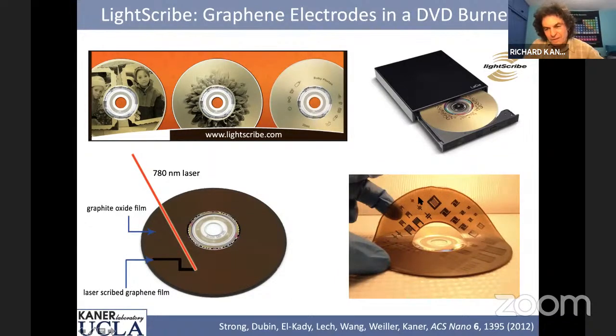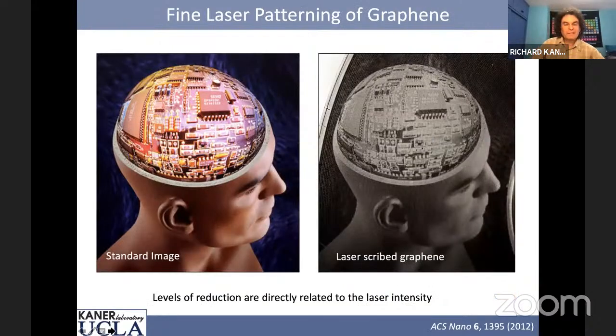So this is graphene oxide on plastic. You can see the golden brown color. You hit it with the laser, and you can draw little circuits. And so basically what we're doing is we're creating graphene, the black conductor, on graphite oxide, the golden brown insulator. And you can use this to make devices. And in fact, you can actually raster any image you like.